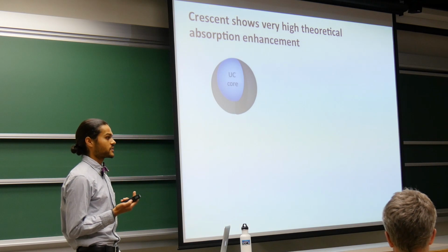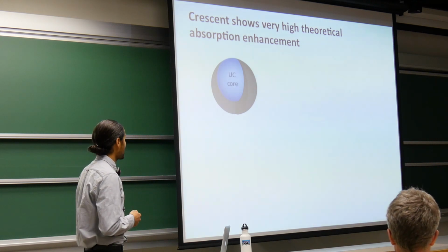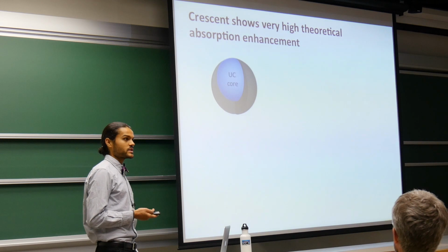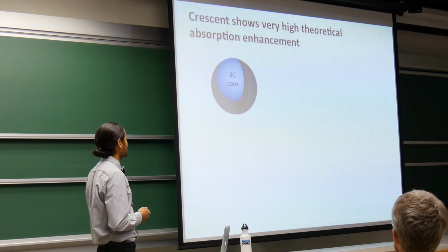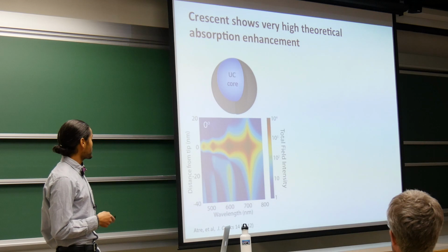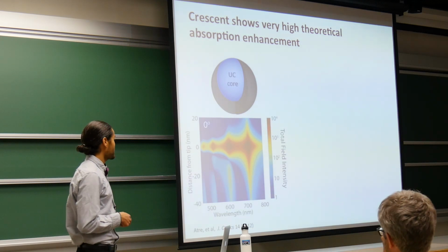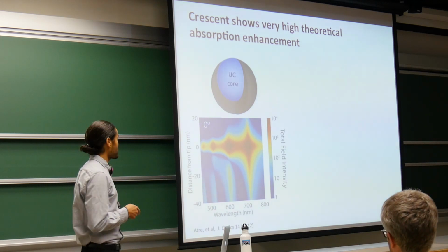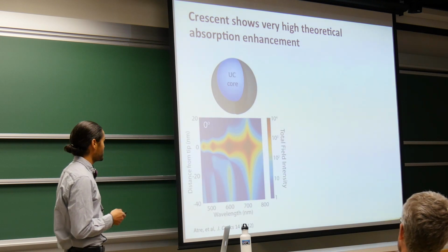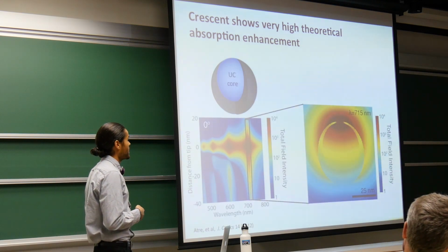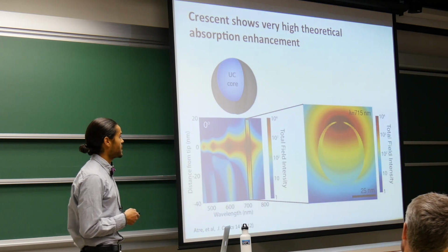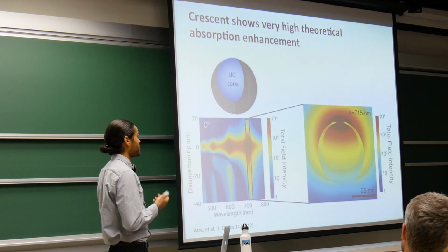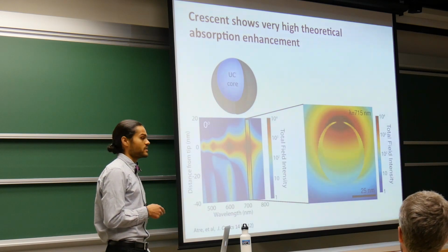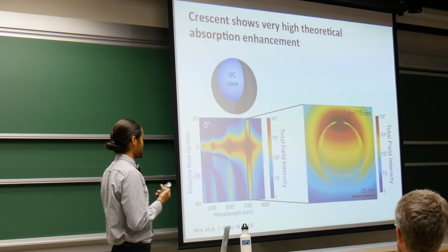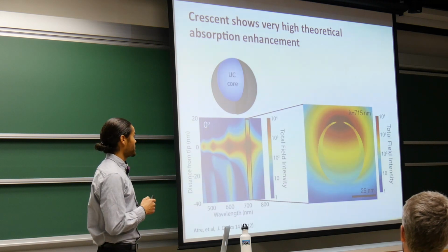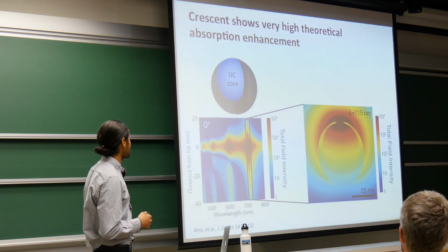If we replace the dielectric core of the crescent with an upconverting core, we should be able to enhance both the absorption and the emission from this upconverting system. If we look at the field enhancement as a function of wavelength throughout this core, we can see that there are multiple resonances that we could make use of. And if we look at the lowest order resonance, in this case, we can see enhancements on the order of at least 100, peaking at around 10,000 near the tips of this structure. So this could significantly improve the absorption qualities of our upconverting system.